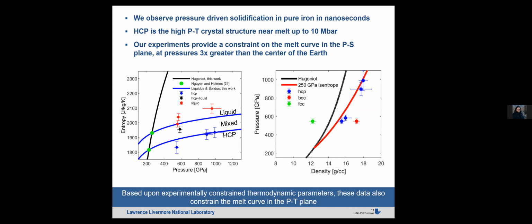I read your paper with great interest, and I have two questions. The first one is related to the crystallization of the core. As I understood, you assume a certain core mantle boundary heat flux and derive the solidification time. But I did not understand the relationship with any interior profile, like a thermal profile for the interior. For example, what happens if a model suggests that the temperature at the very center of the planet is 5000 Kelvin and another model suggests it is 20,000 Kelvin? How is it that this does not depend on the initial temperature that you start crystallizing from?